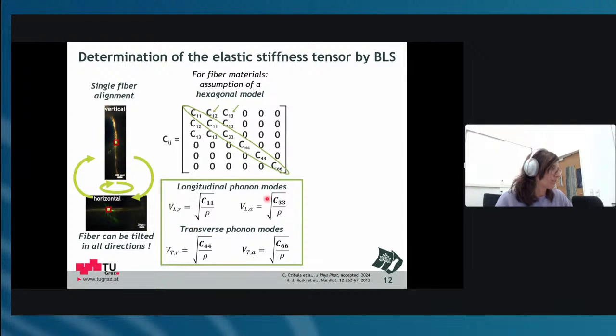For the transverse phonons, or the shear modes in the stiffness tensor, so the C44 and the C66, I can measure the C44 in both alignments, but the C66 I would basically just get in the vertical, or else I need to leave the horizontal alignment, because due to symmetry they will overlap here.